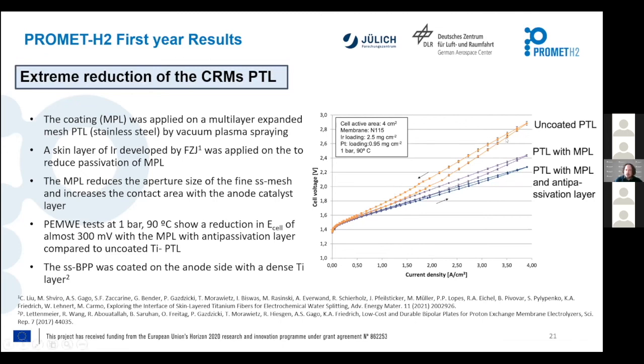And we can compare the uncoated PTLs made of titanium, the PTLs with our coating on stainless steel. And here, last is the one with stainless steel, our coating, and also the anti-passivation layer produced by Jülich. If you want to know more details about this passivation layer, I recommend you read this publication.